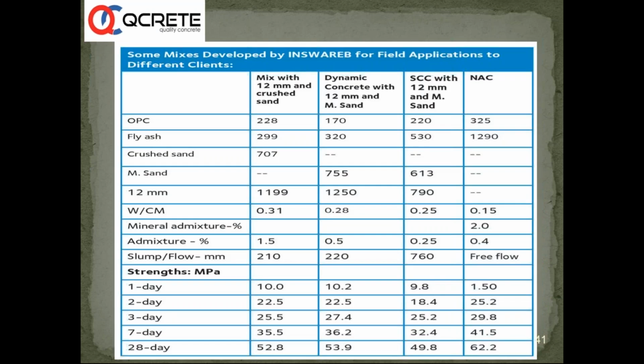So many of the works have been done in India also, where they have developed SCC with different combinations. We can see these mixes here, where you have different SCC concretes made with combinations of a good amount of fly ash, high amount of fly ash. And one of the mixes you can see is where they have removed the crushed sand and used fly ash as a filler material. And you can see the water to cementitious ratio. They have put water to binder ratio as 0.15 actually.